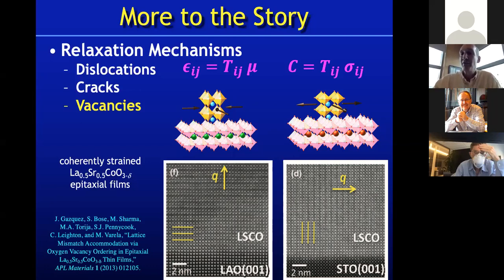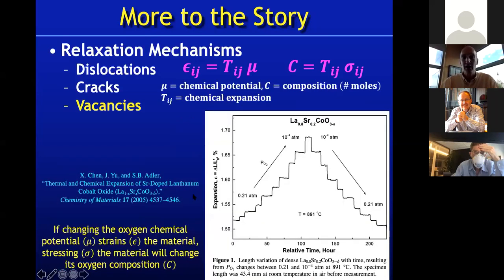Now I've deliberately shown an example of cobalt 4+, which is a system where these vacancies are well known. See if I can go back a slide. So here's a system where this effect has coefficients that are large. Okay, you change the chemical potential, you have huge change in strains. Now, seeing this,